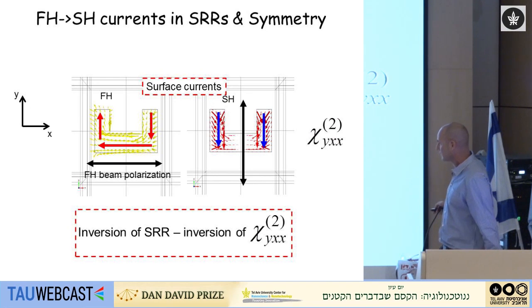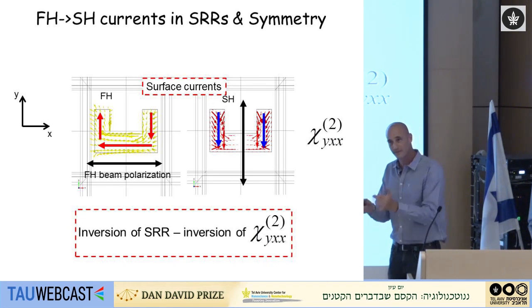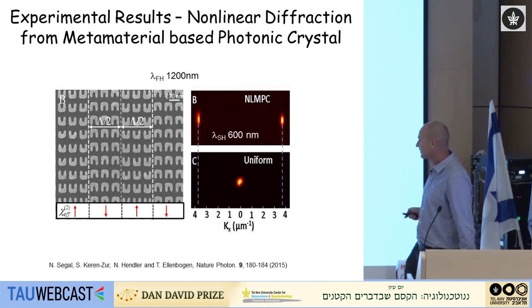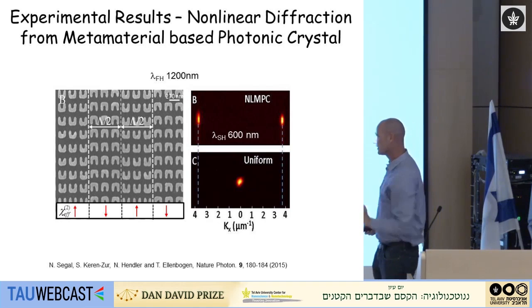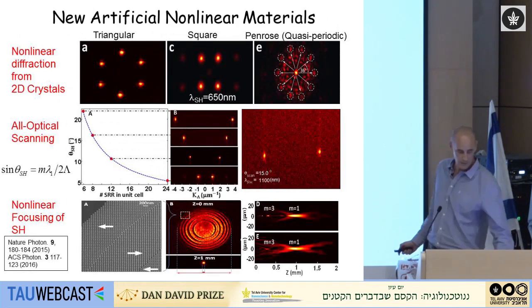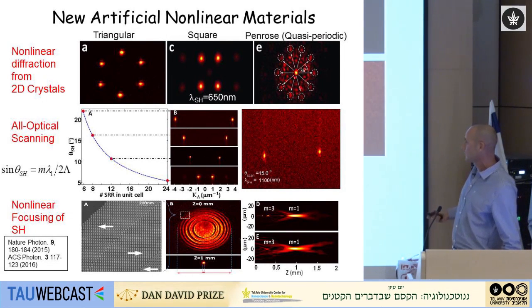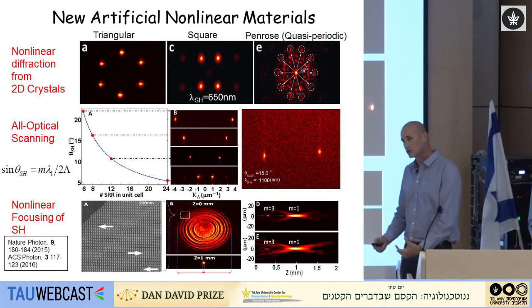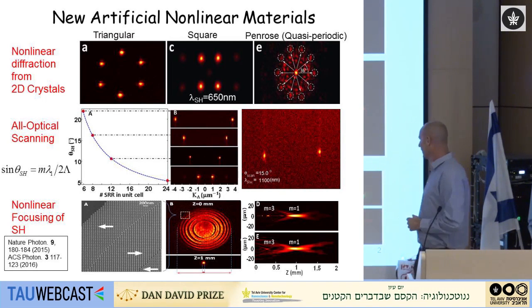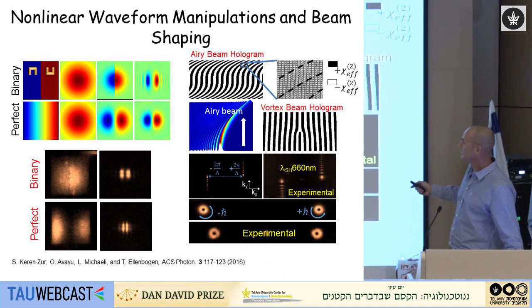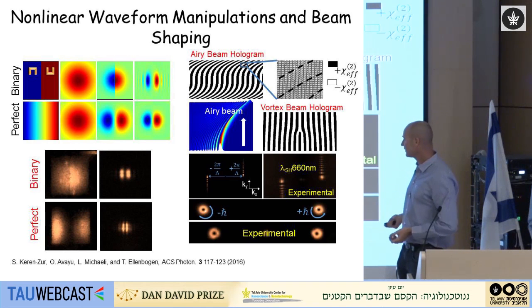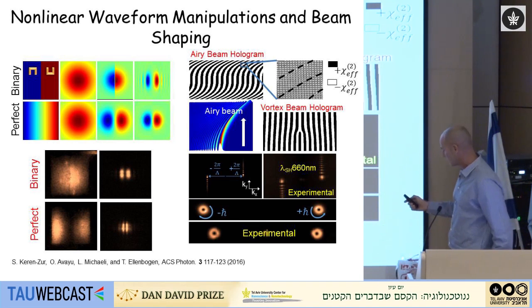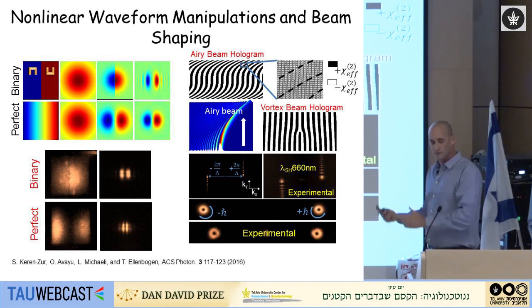This simple operation takes us a long way. We showed that we can use it to create a nonlinear photonic crystal to obtain nonlinear diffraction — shining these samples with a laser beam and making only the second harmonic diffract. We showed two-dimensional nonlinear crystals, second harmonic beams that can be scanned in space, and even a structure that generates second harmonic acting as a lens that focuses to a sample location. We also showed that you are free to shape the waveform of the emitted wave and the beams that go out, with advantages over conventional materials. This opens a new territory for nonlinear optics.